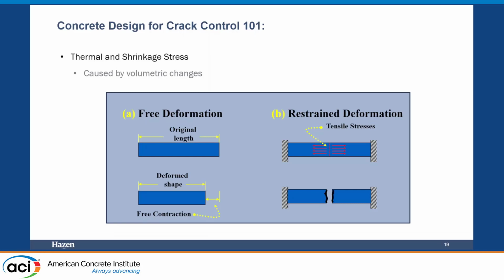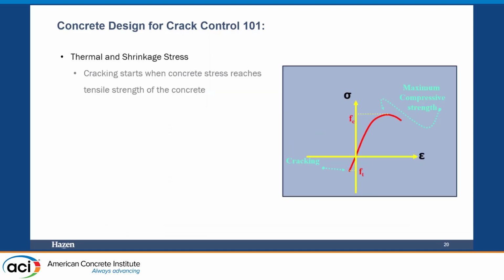You also want to make sure that you have reinforcing designed for the temperature and shrinkage stresses that would be experienced during placement. If concrete is placed and it's free to deform, then it just shrinks and you would experience no stress. But the reality is, after you place the concrete, it's going to be restrained by other elements, beams, columns, walls. There will be something else that restrains it, and when that happens, you're going to get tensile stresses that develop in the concrete. And when the concrete cracks, it is relieving those stresses.